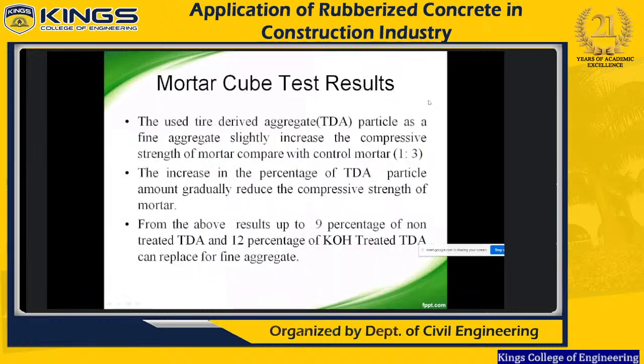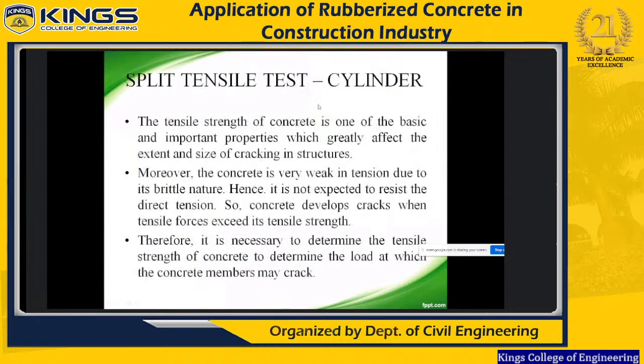These are also the mortar cube test results. We observed that 9% of non-treated and 12% of treated rubber will be good for mortar cubes. Compared with concrete cubes, just 3%, 6% of non-treated rubber and 9% of treated rubber give the optimum strength. So next is split tensile strength.